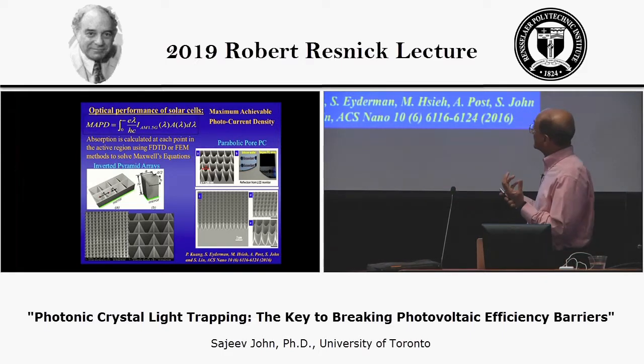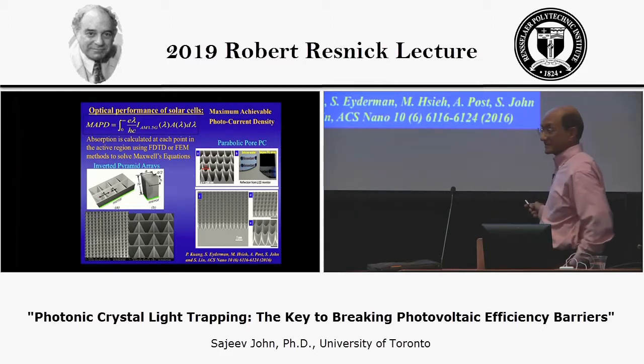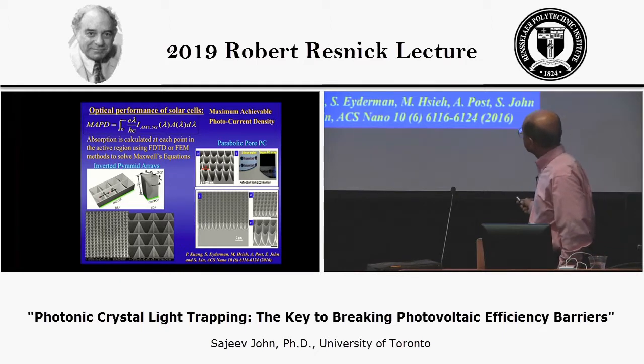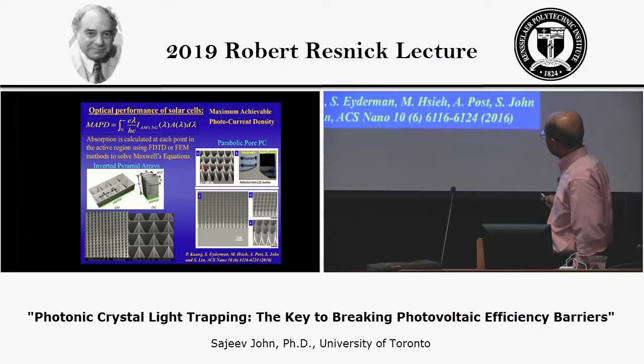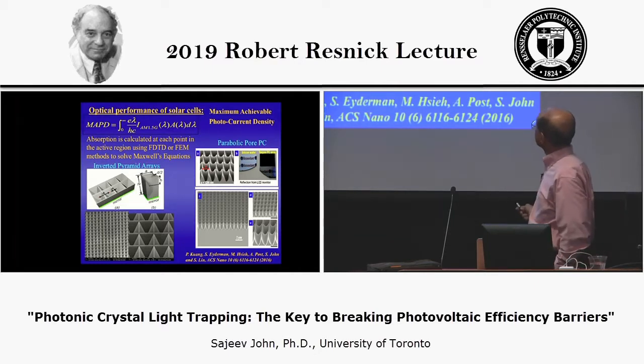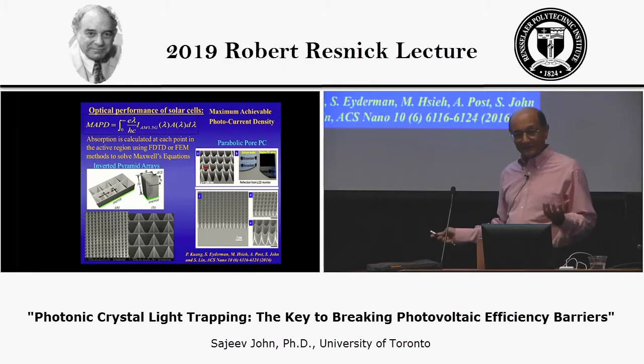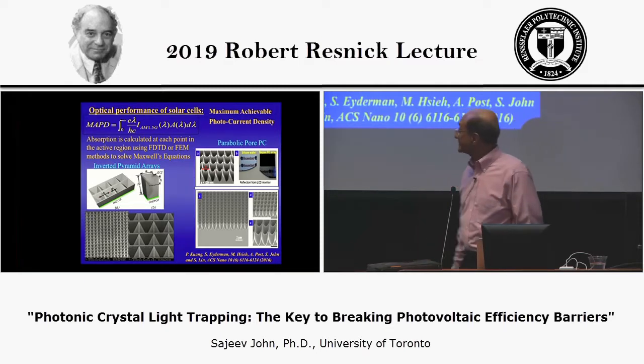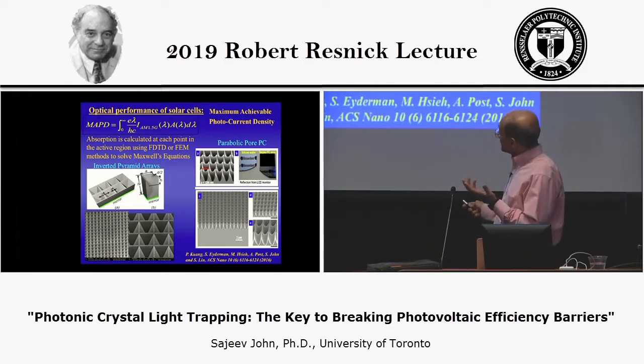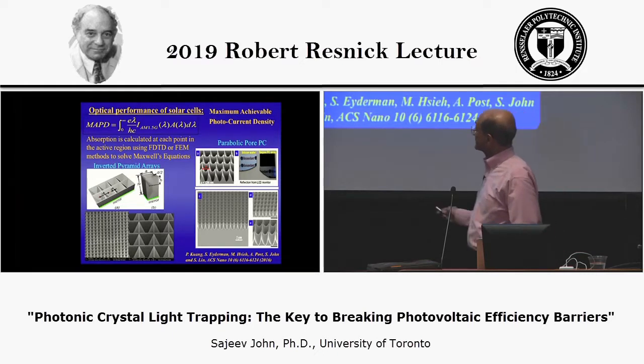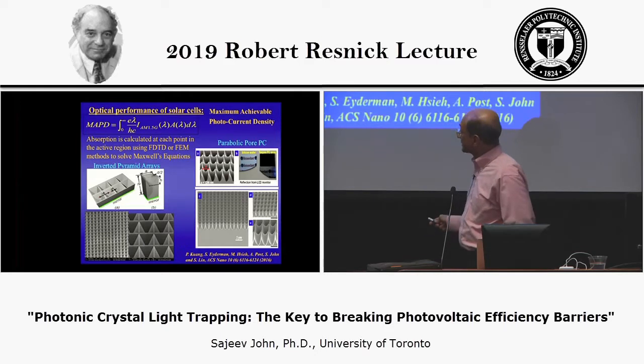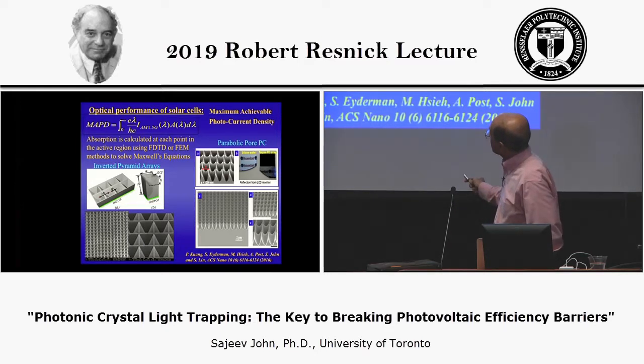And so this is one of the parameters that we'll be looking at in various different structures as I've depicted here. On the right-hand side is a photonic crystal architecture, which was actually developed in Professor Sean Lin's group, which consists of this square lattice array of sort of parabolic-looking pores. The lattice constant here is about 1.2 microns. This is created by a dry etching process. And here's a structure on the left-hand side that even a theorist can make. I actually made this through a national fabrication facility. It is possible to do this very easily because if you apply potassium hydroxide etching, it naturally exposes the 111 surfaces of silicon if you start with the 100 surface. So starting with an appropriate mask, which is made by electron beam lithography, it naturally forms these inverted pyramid structures that are depicted here.